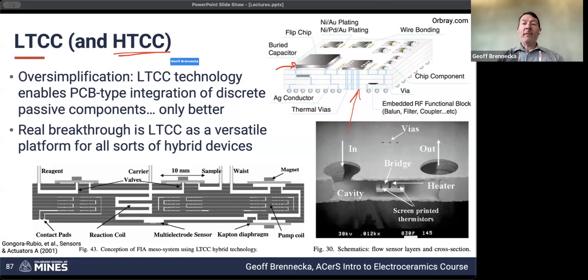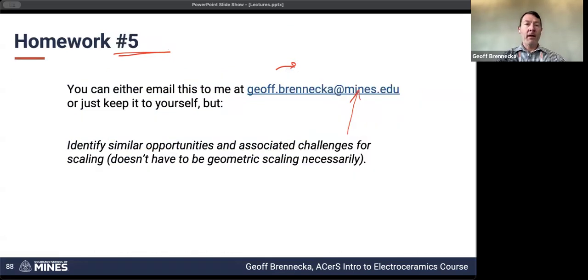HTCC in general uses the same kind of techniques, but less liquid phase and therefore a higher sintering temperature. And so you can't get away with using aluminum or silver wiring. A lot of times the embedded metallization will be platinum or potentially nickel, other types of higher temperature metals. But the HTCCs will therefore have properties that are a little bit closer to raw alumina. So higher elastic modulus, higher operating temperatures, higher hardness, stiffness, all that kind of fun stuff. So those are just some examples.